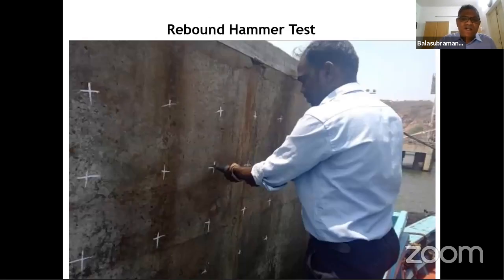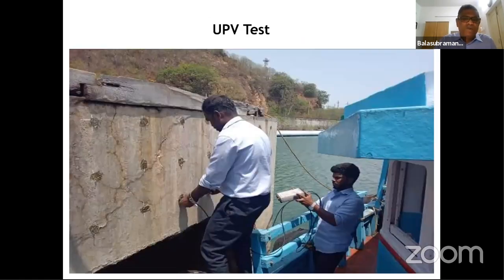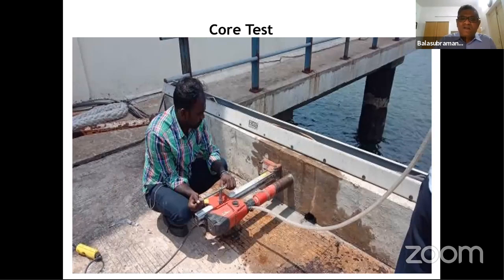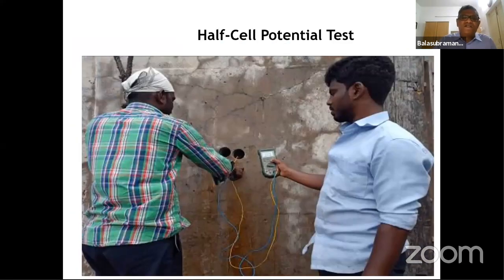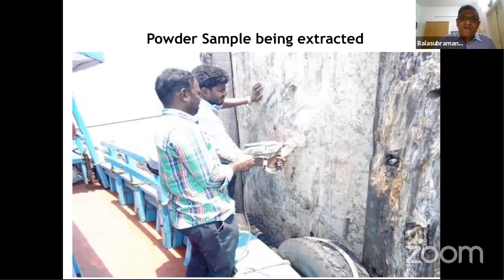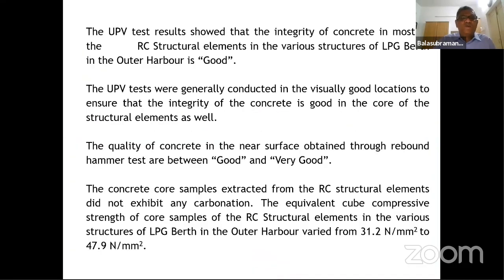So we did NDT testing, rebound hammer, then UPV, and then the core testing, and then half cell potential testing, powder samples, and the summary is that UPV tests showed good results, because UPV tests were generally conducted in the good location. Again, as in the case of half cell potential test, you can't go and do a UPV test on a bad location, you'll get definitely bad results. So when you're giving a bill of quantity, you have to be very sure. I cannot give a bill of quantity only for the bad location.